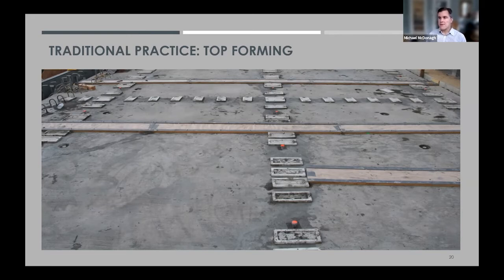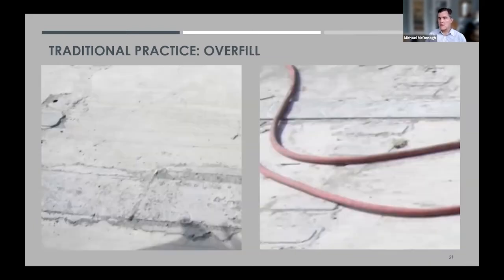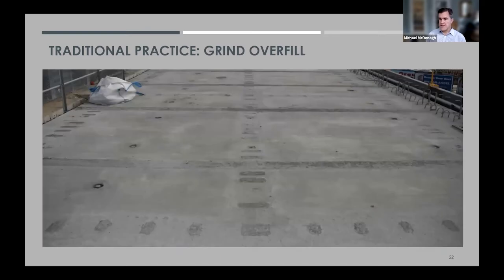And then once you top form, now you are creating the risk of trapping air that may be escaping. So most agencies then require that the connections be overfilled, which you can kind of see in these photos, so that any air that gets trapped under the form is above the level of the deck, and then that will get ground away, leaving you a flush surface.